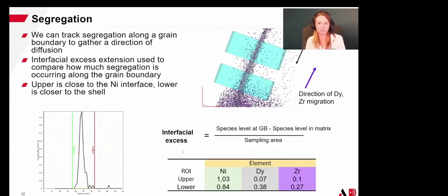Now, once we do this interfacial excess calculation, we can compare that for different elements as we go to different regions. So here I've called this upper region closer to the electrode, and the lower region is closer to the matrix. Now, one thing that we find, which is maybe not that surprising, is that we have quite a bit more nickel closer to the electrode. Well, that's an interesting observation because nickel's a metallic element. So if we see diffusion from our metallic electrode into our ceramic, which is supposed to be insulating, this can be pretty detrimental to the operation of the device because you now have metal migration into your ceramic insulator.